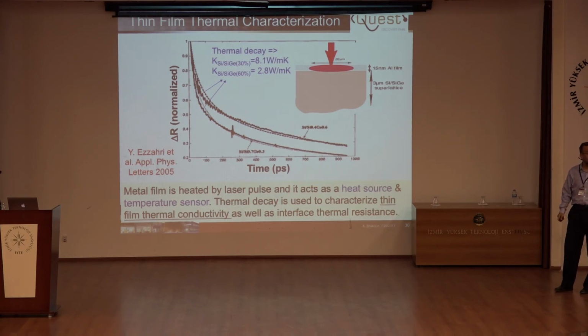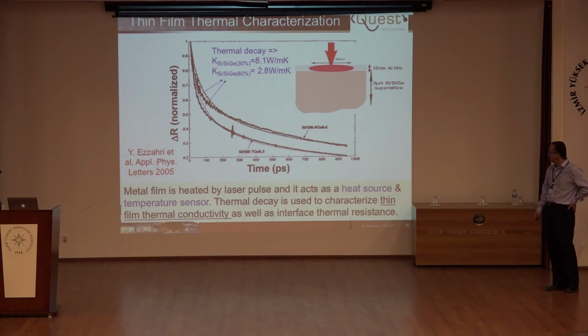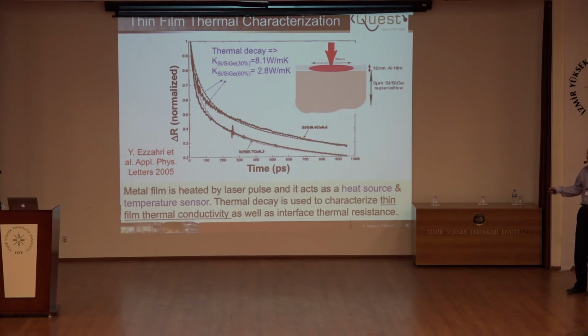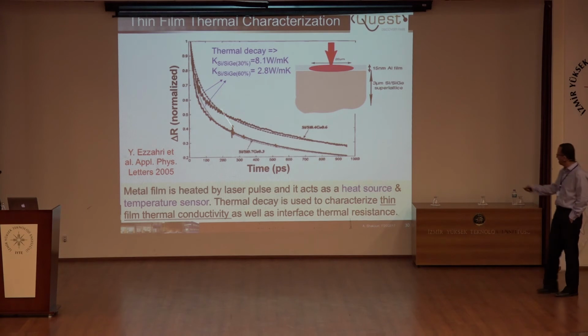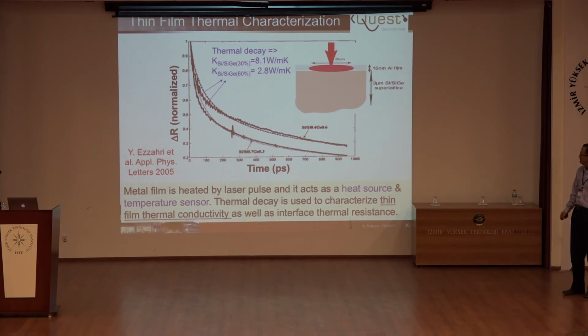You don't need modeling. By eye, you know that this sample should have a higher thermal conductivity than this one, correct? The higher the thermal conductivity, the faster the heat from here goes down. About 10 years ago, when we were naive, we thought, this is the fit based on Fourier, and we get a thermal conductivity, beautiful, 2.8, and if you're careful, maybe we can give another digit. There are some tiny variations, but if you're an experimentalist, you know that you cannot fit everything perfectly all the time. This is a good trend. You can publish in good papers about that.